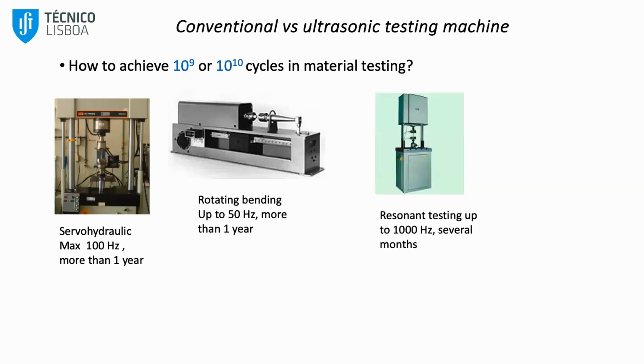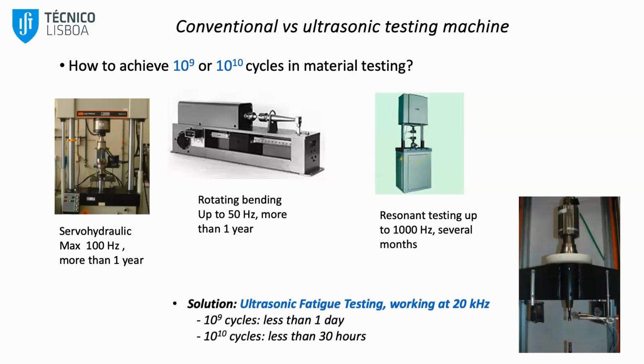Just to compare with the classical machines, if you want to achieve 10 to the power 9 or 10 to the power 10 cycles, we take a lot of time to do that. So, costs and money and time. We need another way to perform this type of test. So we are using an ultrasonic fatigue testing machine that works at 20 kilohertz. If you don't stop the test, which is not the real case in most cases, it takes less than a day. And if you want to achieve 10 to the power 10, it's less than 30 hours.